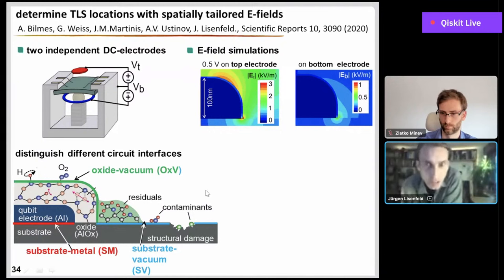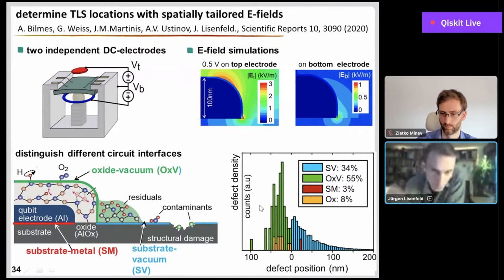And one such analysis produces such a result, for example. And in our tested qubit, we found that the major contribution to defects were actually the defects which are residing at the very surface of this oxide layer here. And the second largest contribution were the defects here on the substrate, while at the substrate-metal interface we found only a few defects, which is also explained because this is typically the cleanest interface that you can make in your fabrication. It's the first thing that you do, just depositing the metal on the pristine substrate. So this was expected actually.